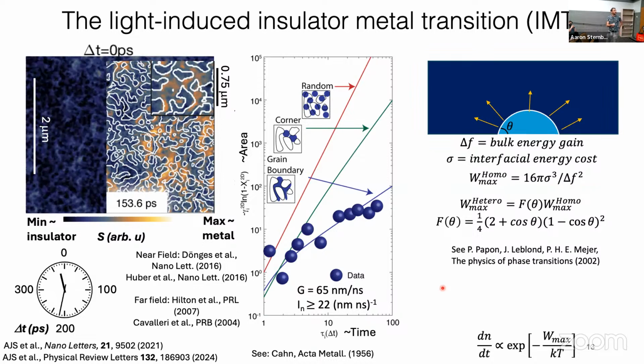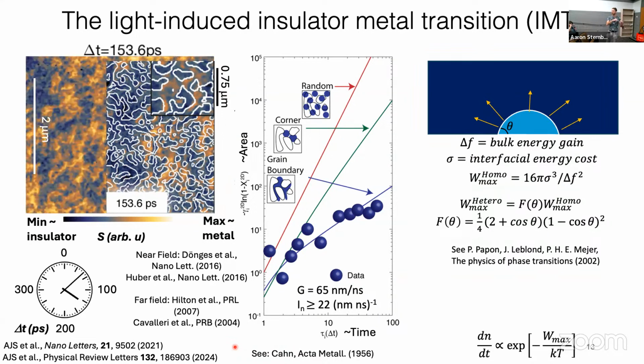So all of this seems to indicate that the system is inhomogeneous, and a big part of that is the presence of boundaries. But this is a complicated system. There are strain fields, there are grain boundaries, there are twin domains, there are possible chemical inhomogeneities and stoichiometry, and all of these things are playing a role. I just want to stress that these are qualitative inferences, and we're really just beginning to learn about nucleation and growth, even of just the electronic transition in these films.